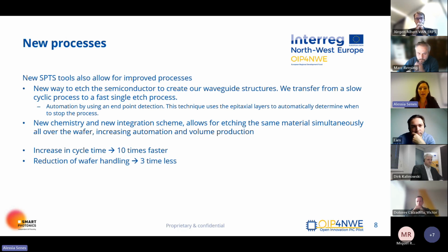Then in the project, not only new tools were bought and installed, but these tools also enabled improved processes. For example, what we did at Smart Photonics, we developed a new way to etch the semiconductor to create our waveguide structures. And we moved from the previous slow cyclic process to a fast single etch process. The automation is done by using an endpoint detection, and this technique uses the epitaxial layer to automatically determine when to stop the process. We also developed new chemistry and new integration scheme that allows for etching the same material simultaneously all over the wafer, and this increases automation for volume production.